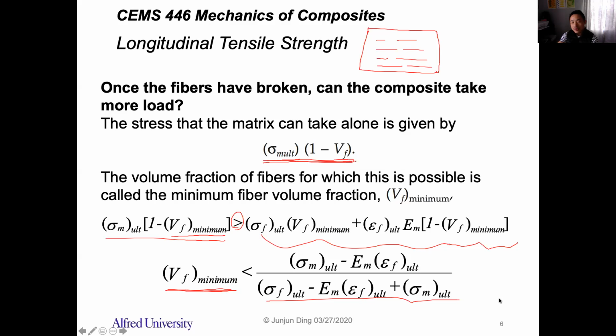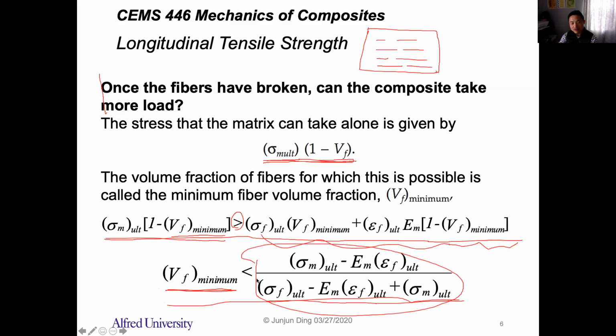Is that right? So the key is that if you want to find out if the composite can take more load after the fibers are broken, you have to derive it based on this equation, right? This relation. So this relation means the composite can take more load, right? This is the higher ultimate strength after the fiber breaks, and this is the ultimate strength before the fiber is broken. So therefore, you can find out the minimum volume fraction of the fiber. So if the volume fraction of the fiber is less than this value, that means the composite will not completely fail after the fibers are broken. Right? Does that make sense?